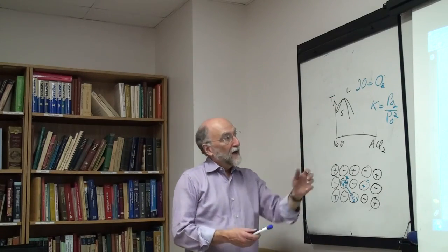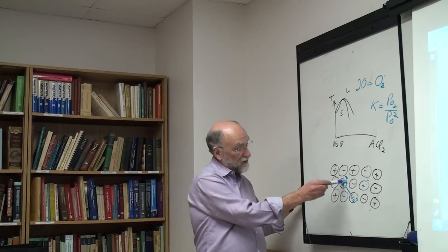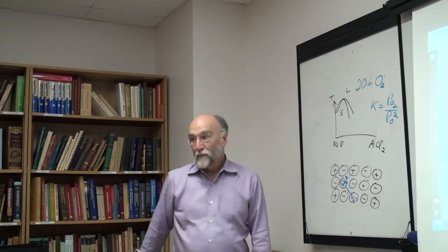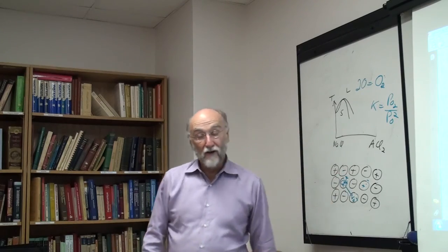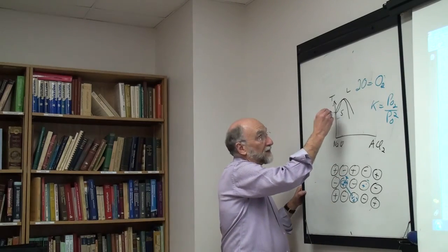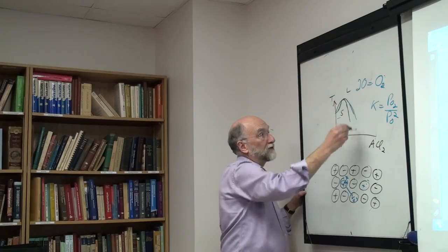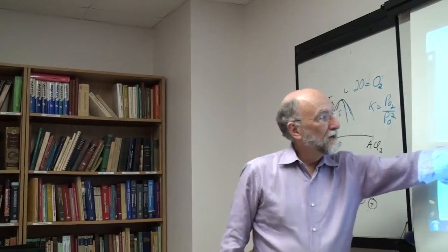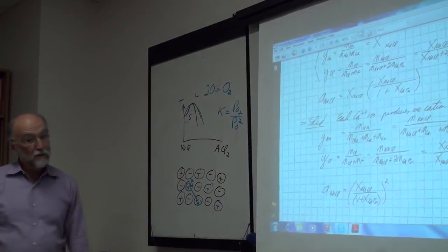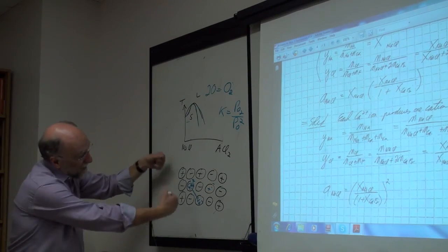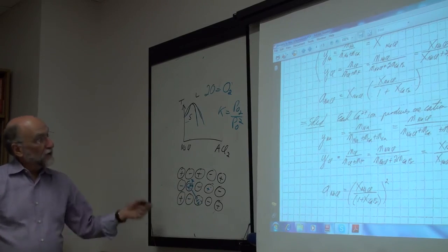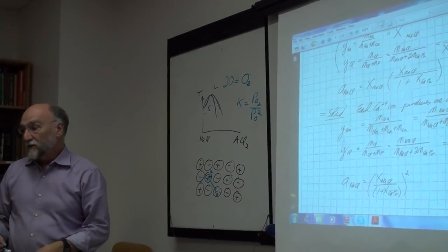Okay. So as you approach very, very dilute solutions, the calciums and vacancies come apart, but as you get more concentrated solutions, then they're going to come together. That's why this effect here is really only very small. So this type of equation really is only going to apply up to 1 or 2% depending on the system. And then as you get further on, then you're going to start to have cation vacancy associates form, and it's going to come back down again.